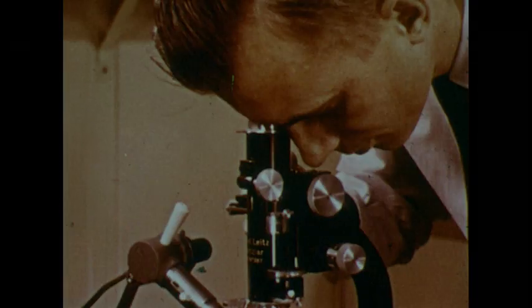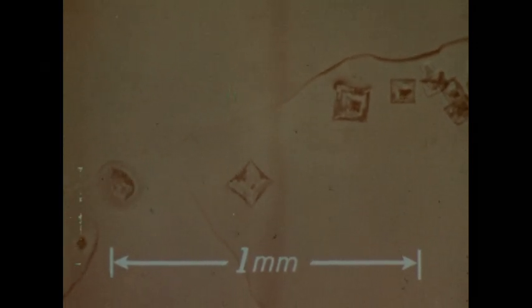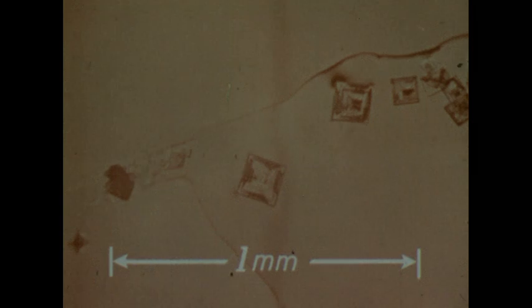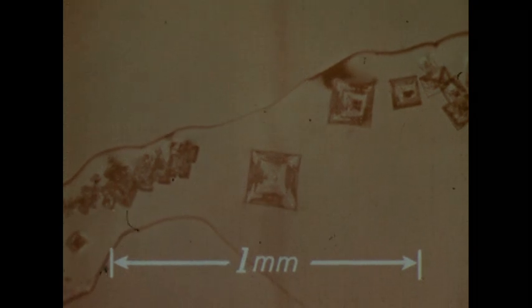Water will evaporate, and the salt will... Here it comes, crystallizing in regular shapes, all with rectangular outlines. The fact that they're nearly square in cross-section, and stay that way as they grow, means that the crystal is accumulating sodium and chlorine atoms about as rapidly on one face as on another. If the crystals could keep on growing, uninhibited by obstructions or lack of solution, they would grow large like this one.